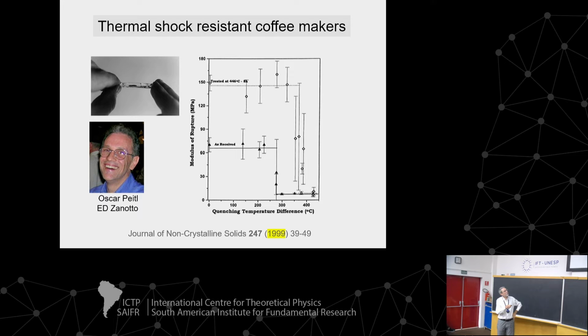So the normal coffee makers break with a thermal shock of about 270 degrees Celsius. That's very useful information for you. This is the limit of your coffee makers, 270 degrees Celsius. So after some work, it was his thesis actually, we treated the glass, we optimized the process, and improved the strength to 370 degrees Celsius. 100 degrees Celsius more, and the actual fracture strength also tripled or so. So this is the actual strength, and this is the thermal shock limit.